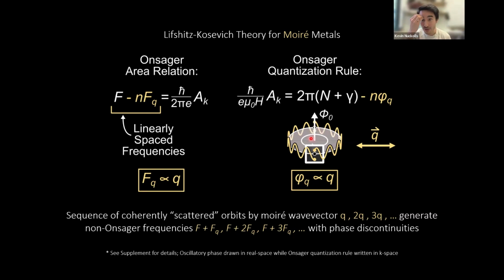So all of this framework is really nice because it gives us an understanding of what's going on in our system, that the Moiré superlattice is generating a coherent set of different cyclotron orbits that have these kind of scattered wave vectors. But this is a non-Onsager mechanism. Looking at this theory, it's mathematically satisfying, but intuitively it's very hard to picture, particularly because it has this weird phase discontinuity that I don't see familiar in quantum mechanics. But we were able to see that actually this is much more naturally understood when we elevate the system into 4 dimensions, into 4-dimensional superspace.